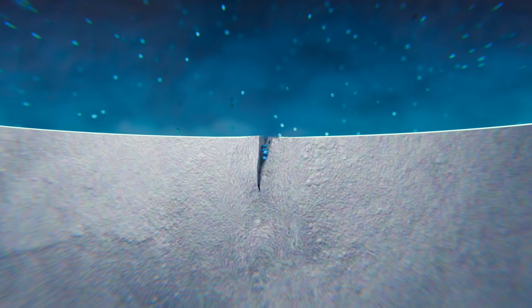Any resulting plastic deformation at the crack tip would momentarily rupture the protective chromium oxide film, which the chloride ions in the environment then prevented from reforming. Without the protective film, the chloride-rich, oxygen-containing environment could attack the exposed metal at the crack tip, steadily growing the cracks. Temperature played a key role too, with the elevated temperatures in the pool hall making chloride SCC much more likely.